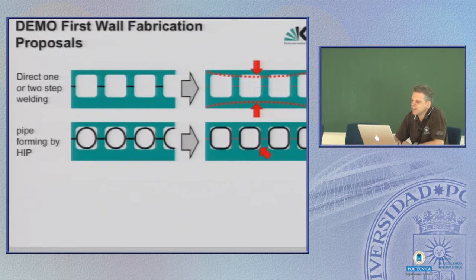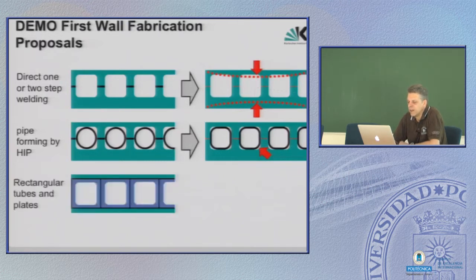However, as indicated here, this always leaves more or less an extended part which is not bonded to the plate. And this again is not what you want in a high heat flux loaded part, because later on the cooling channels will be overheated and will not work properly.